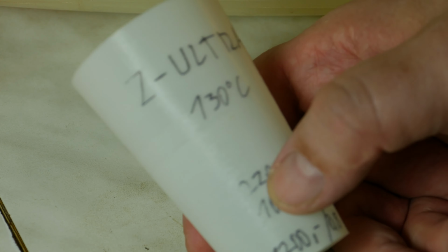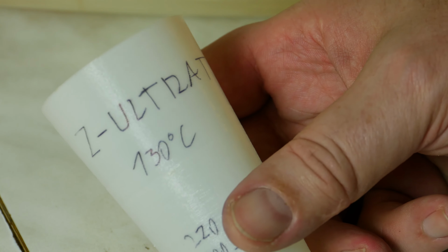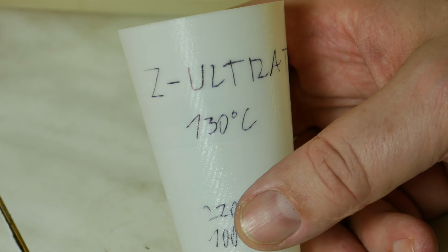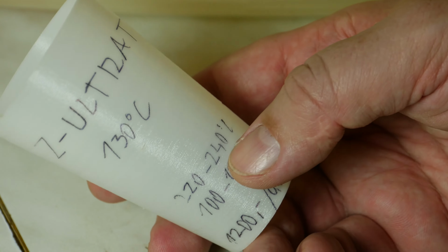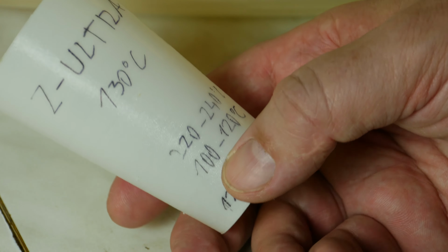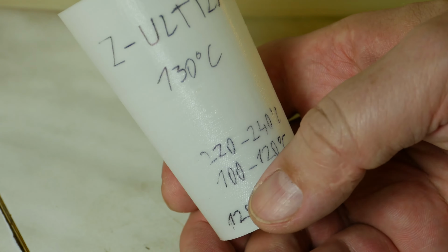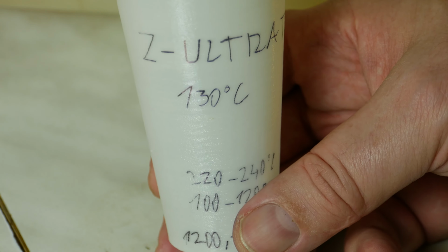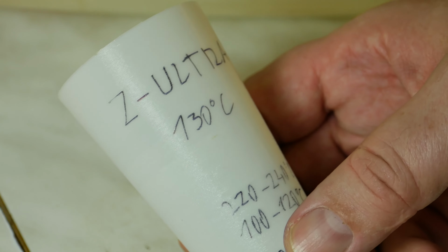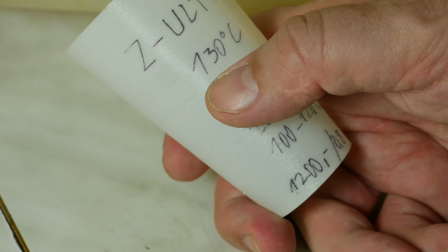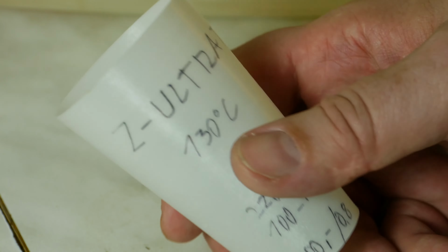And number one about temperature resistance without any special procedure like annealing, and without a special price, without a special print procedure, is Z-UltraT, again by Pro 3D company. The same company which makes HD-PLA makes Z-UltraT filament. Print procedure is similar to ABS or ASA. It means hot end temperature 220 to 240 degrees Celsius, hot bed about 100 to 120. Price is higher, maybe 3 times that of normal PLA, but after print, without any next procedure, you will have 130 degrees Celsius temperature resistance.